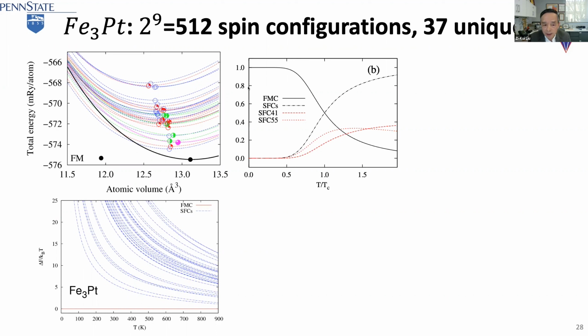So you can calculate the probability using the Zentropy theory. At 0 Kelvin, 100% is the ground state, but as the temperature increases, around 200 degrees, you start to see the transition. The probability of the stable configuration decreases because you don't have one, you have 510 other ones, much more than that. And then at some temperature, which I believe is 275 or 300, I should put the temperature here, this one becomes less than 50%, even though it still has the lowest energy.